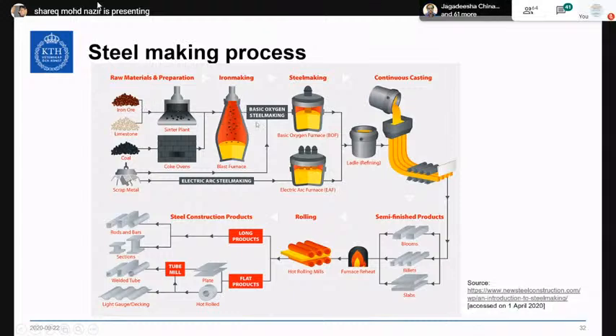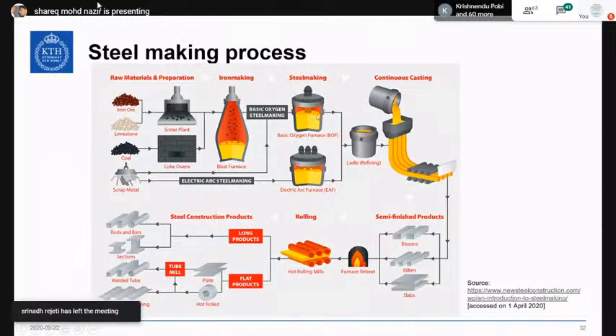The ore gets reduced to around 93-94% iron, and that is passed on to the basic oxygen furnace, where you supply oxygen to oxidize the other metals that have been formed, for example, silicon and manganese. So you form SiO2 and manganese oxide, and a bit of iron also goes into iron oxide form, but the majority of the iron remains here, and then this is around 98% to 99% iron. This is taken into a ladle, and then it is continuously casted in the form you want. In the electric arc furnace, you basically melt the scrap, and in the other technologies, we also put the pig iron in the electric arc furnace. We put the direct reduced iron in the electric arc furnace.